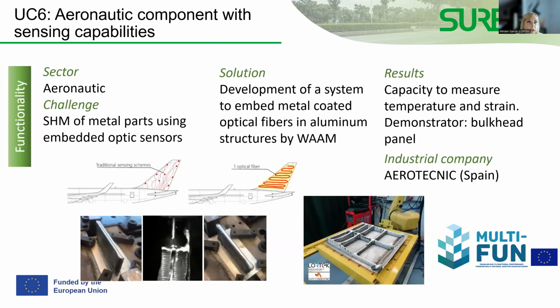Then the sixth use case is an aeronautic component with sensing capabilities. So here, it's something different. Here, what we wanted to improve was the functionality of the parts. So Aerotechnic, which is an SME as well, wanted to include optic sensors within different parts for the aircraft in order to make structural health monitoring of the parts. So we developed a system to embed some metal-coated optical fibers in aluminum structures using WAAM technology, wire arc additive manufacturing. And we found out that the resulting part had the capacity to measure the temperature and the strain within the parts. So that is what we really wanted to achieve.